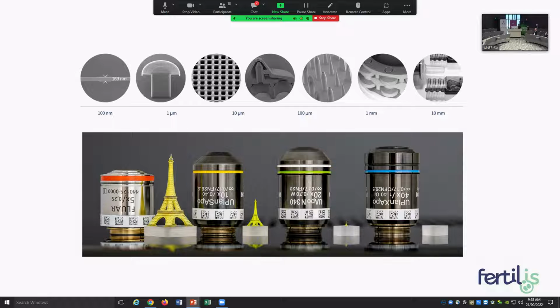The Nano One is fast. With up to 100 times higher throughput for production cycles, it supports scan speeds of up to 1,000 millimetres per second and throughput rates of 450 cubic millimetres per hour, which enables prototyping as well as production. It is not just the fastest in the market, it is fastest by far. So it can print in 5.5 minutes what a competitor technology can print in 163 minutes. That's pretty impressive.